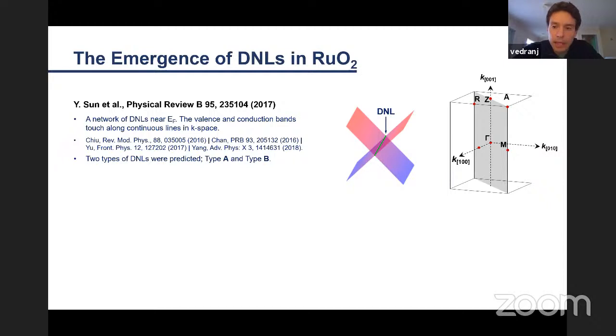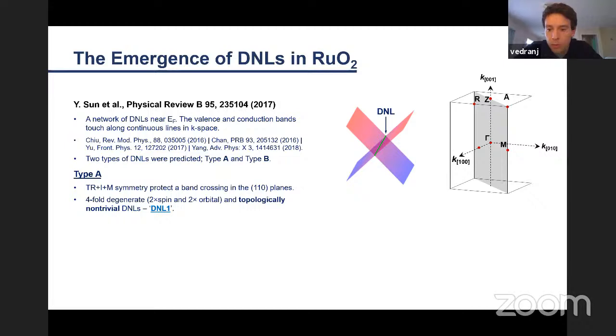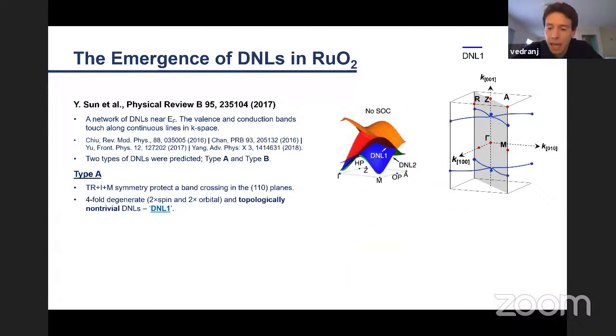The type A Dirac nodal lines have time reversal and inversion symmetry, and in unison with a mirror symmetry, they protect a band crossing within the 110 family of planes. This produces a network of these fourfold degenerate, two-spin, two-orbital, and topologically non-trivial Dirac nodal lines. And they are outlined here in the Brillouin zone. This is how they look in momentum space.